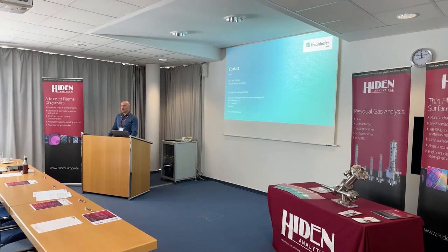How do you bend the plasma at 90 degrees? With some coil, magnetically. And do you see some coating already on the coil? The coil is covered, so there are no coatings on the coil. Is it like some kind of electrostatic deflection of the plasma ions or species? How do you actually bend it? No, it's purely magnetically bent. Then you have some high flux in the middle of your coil, and this is bent by 90 degrees.